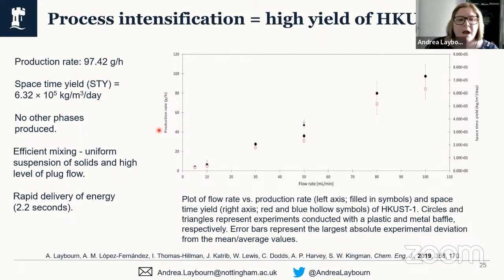If you wanted to pressurize, or go above the boiling point of your solvent, you would need to incorporate one of those. So what we've got on this slide is the production rate in grams per hour versus the flow rate. And we wanted to just get a first look and see if we were able to produce the material at a range of different flow rates. And we can see that as you increase the flow rate, the production rate increases, which is what you would expect, because you're putting through more of the reagent, you're heating the reagents, and then being able to produce more of that because your throughput is higher. So that was an excellent checkpoint.